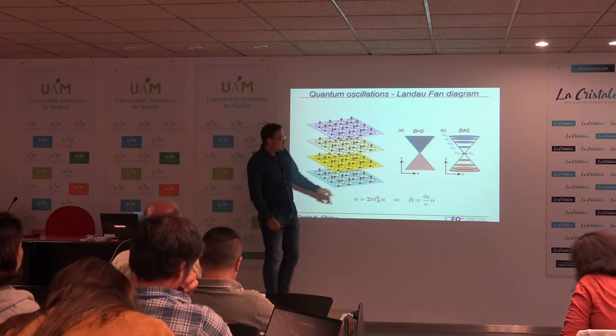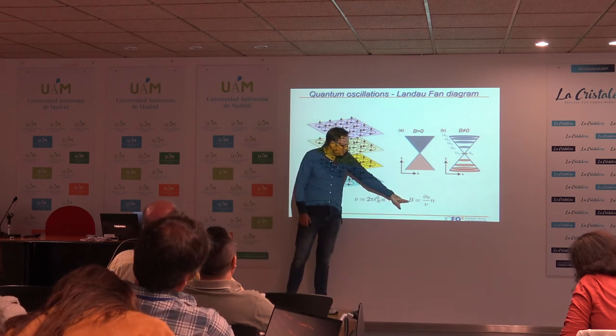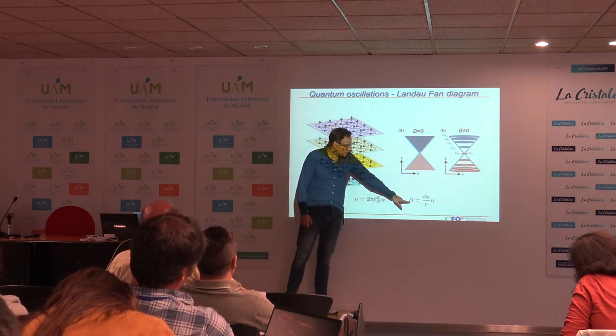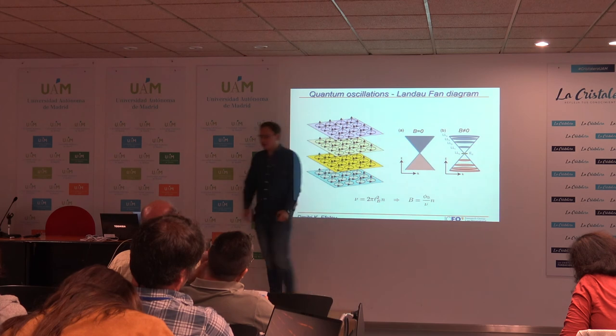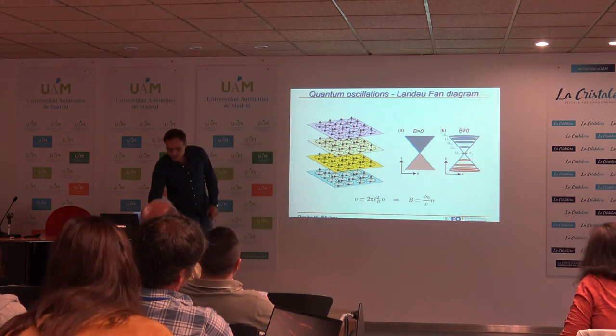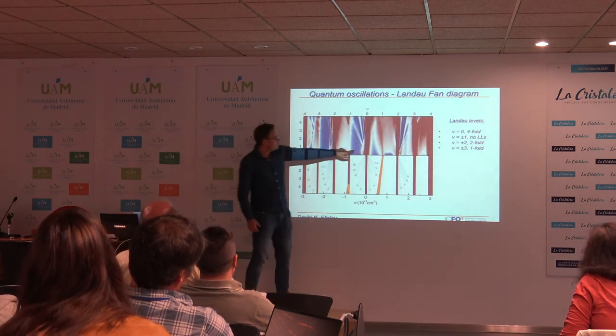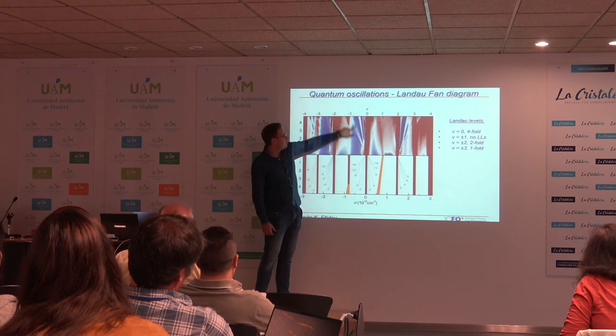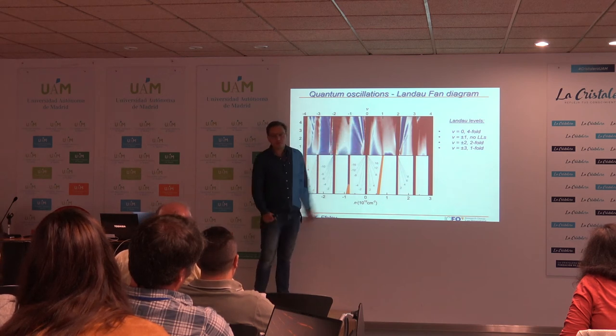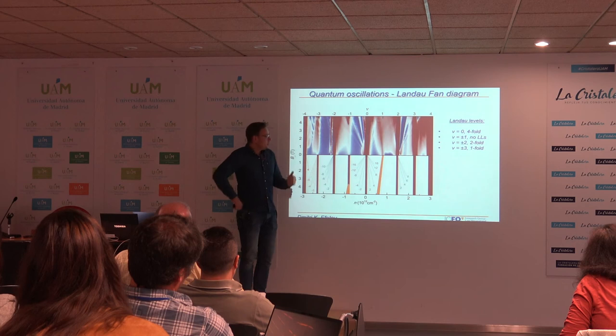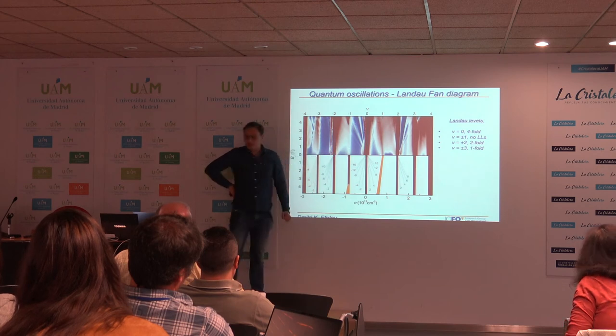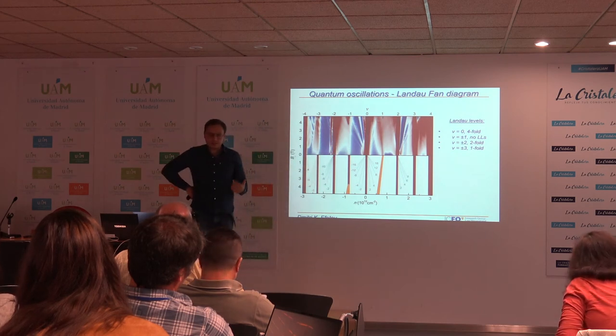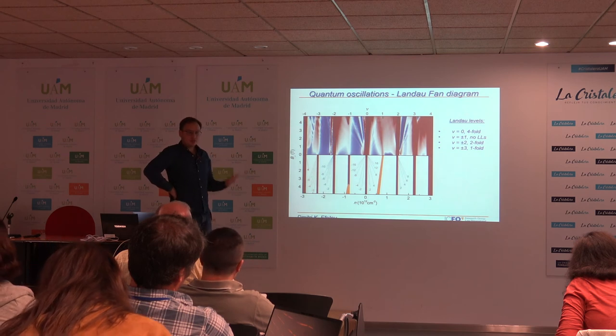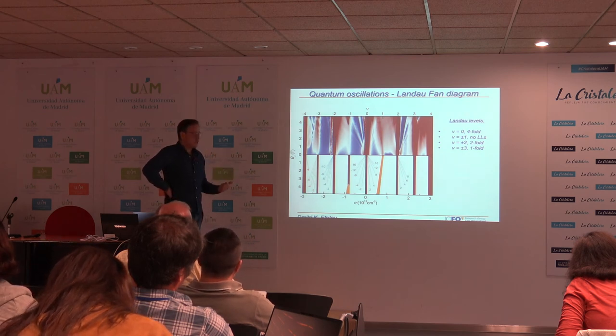And then the relationship which you get in the end is that really, for each Landau level, the dependence between magnetic field and carrier density is linear. And really, what this means is that all these linear lines here, in the end, each is an individual Landau level. So from the slope of each individual Landau level, we can tell how many electrons per unit cell each Landau level could take.